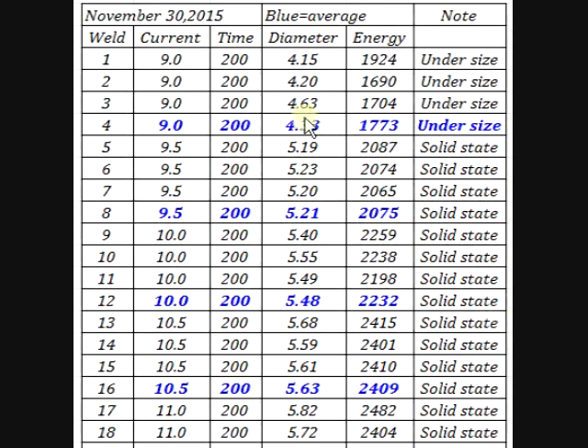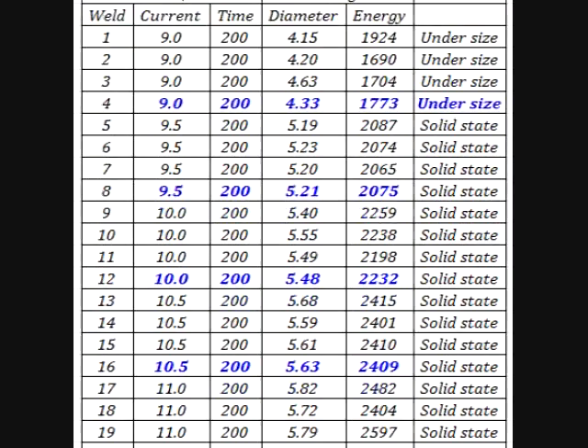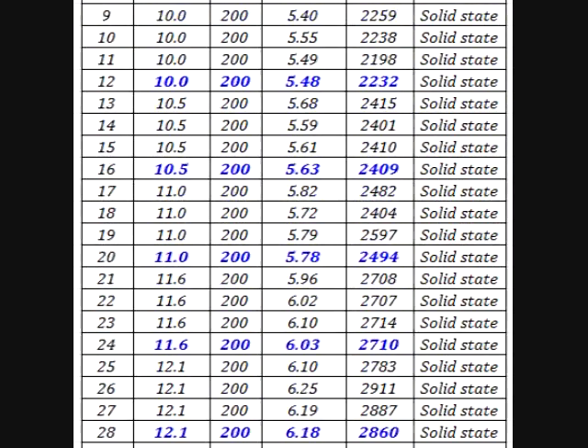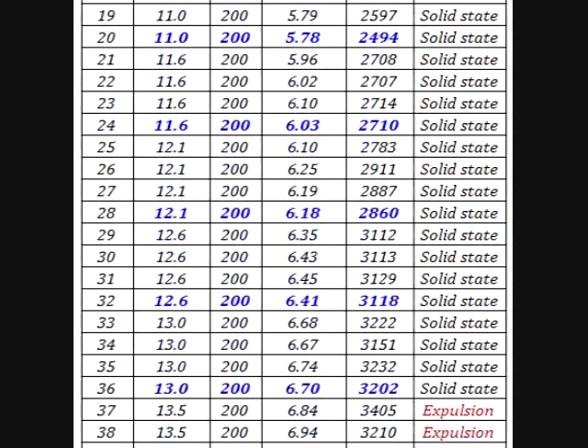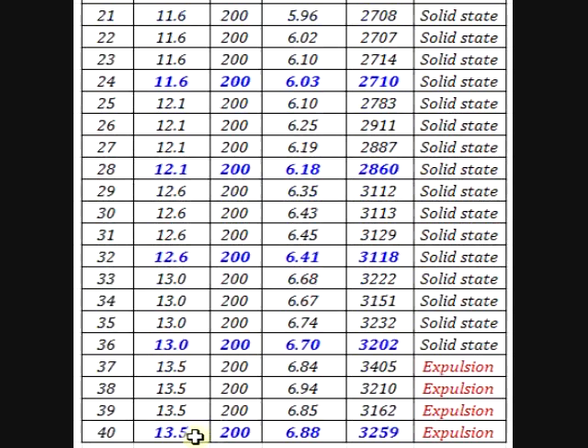This is the constant time, variable current plot, energy plot. We started with 9.0 kiloampere, and we found the nugget is less than 5 millimeters, so we keep on going until 13.5 kiloampere. These 4 welds are expulsion welds, so we will not count them in the system.